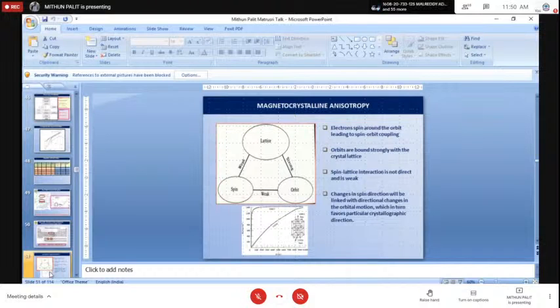So if we perform some kind of hybridization between these two, we can take advantage of the high Curie temperature of the transition metal and the strong spin orbit coupling of the rare earth metal. Strong spin orbit coupling is actually very important because now your spins are coupled with the orbit. So the magnet will not so easily be demagnetized under the external influence of a negative magnetic field. That is called strong magnetocrystalline anisotropy.